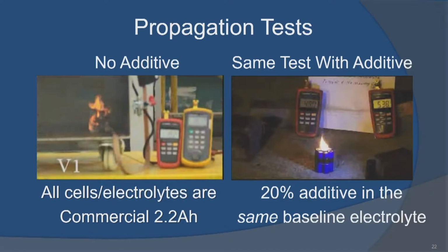I'd be glad to show this offline because these screen captures are actually parts of a movie. And what we've done is we showed that the middle cell, which we intentionally made misbehave, it catches on fire. What do its neighbors do? Well, with no additive, everybody joins the party and plays, and you have a really, really exciting fire. Now, I say exciting as a scientist, but if it was in my pocket, it would be very much less exciting. In the exact same test, with the exact same commercially produced cells, with our additive, we make the center cell misbehave. Nobody else cares. Not only do they not catch on fire, they still perform adequately.